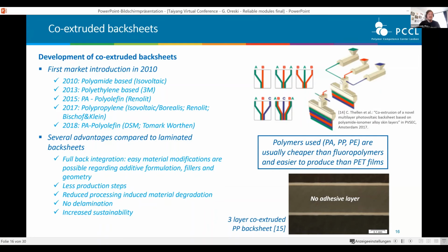We have therefore reduced processing-induced material degradation. We don't expect delamination, and in most cases we also have increased sustainability. And the polymers used, polyamide, polypropylene, polyethylene, are usually cheaper than fluoropolymers or the PET films. What is still missing, and I think we will hear something later on from Kaushik from DuPont, is the track record. PVF has a track record of more than 40 years outdoors. That's a thing we still have to achieve for this kind of backsheets.